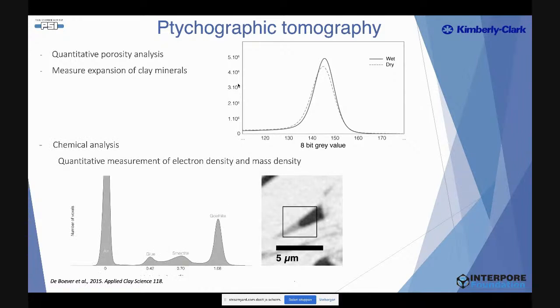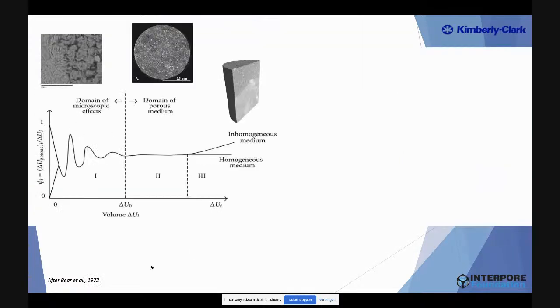And this technique also allows you to do chemical analysis. For instance, we analyzed the liquid that we could clearly see here inside. Based on the quantitative measurements of the electron density and mass density, we were able to say that this liquid was the glue inside our pores, so the glue that was used to put our sample on our sample holder. So you also get chemical information.